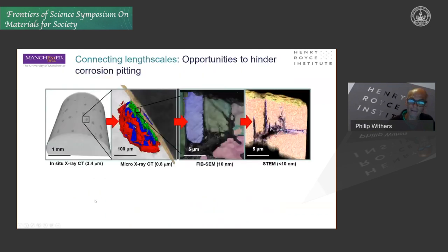So if we look at the millimeter scale, we can look at the efficacy of paints to inhibit corrosion and the use of inhibitors in reducing corrosion rates, and we can follow that in real time in the X-ray computed tomography. We can then go down to this fine scale to study the pit, which is shown here in blue, and the corrosion cracks which are emanating from it in red. And clearly the pit is of structural integrity concern, but the corrosion cracks are much more of a high threat in terms of structural integrity. And we can see those corrosion cracks. If we can control the emanation of the cracks from the pit, then we can end up with a safer